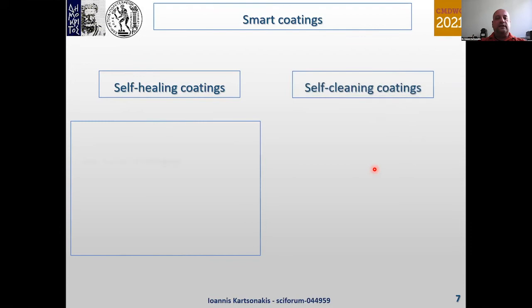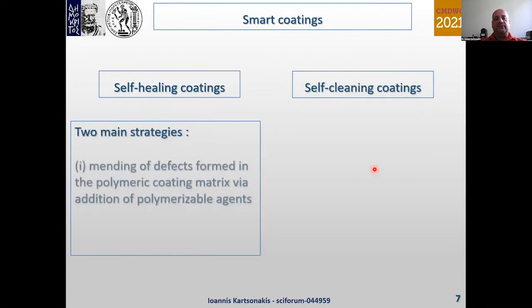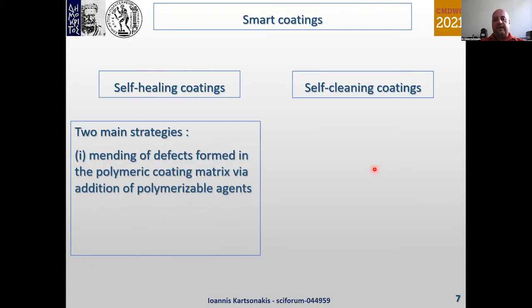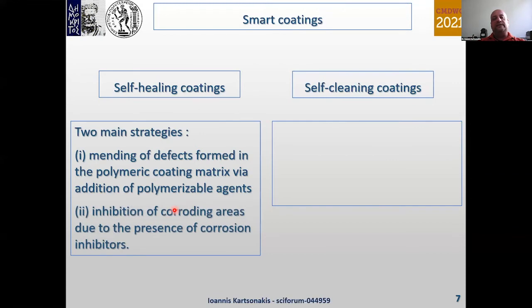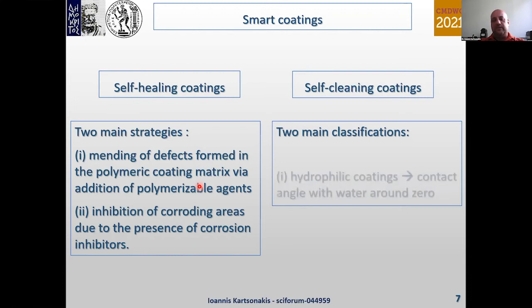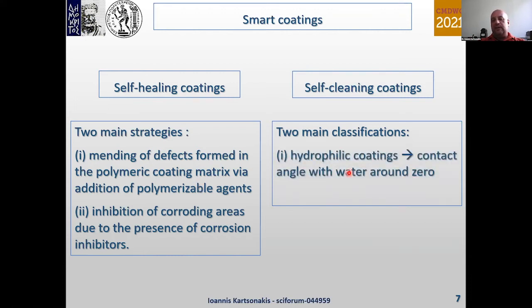Regarding the self-healing coatings, two main strategies can be mentioned. The first one is mending of defects formed in the polymeric coating matrix by addition of agents that can be polymerized. The second main strategy is inhibition of corroding areas due to the presence of corrosion inhibitors, either anodic or cathodic inhibitors. Regarding the self-cleaning coatings, two main classifications can be mentioned. Hydrophilic coatings, that has to do with a contact angle with water that is around 0. And another classification is hydrophobic coatings.